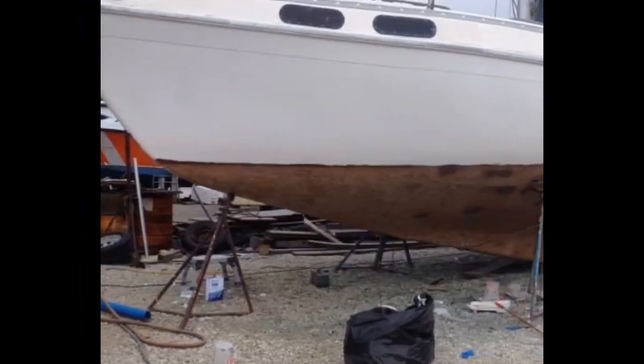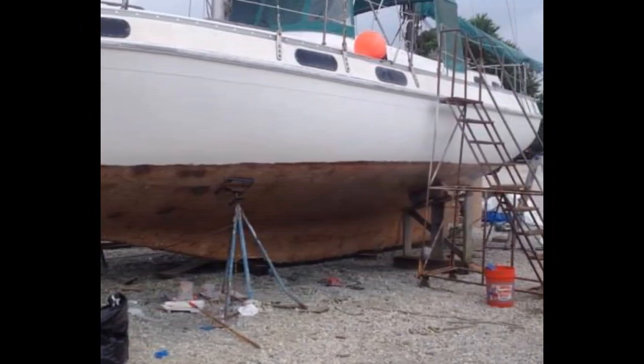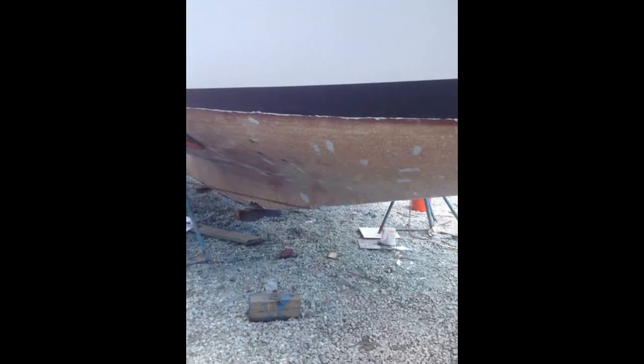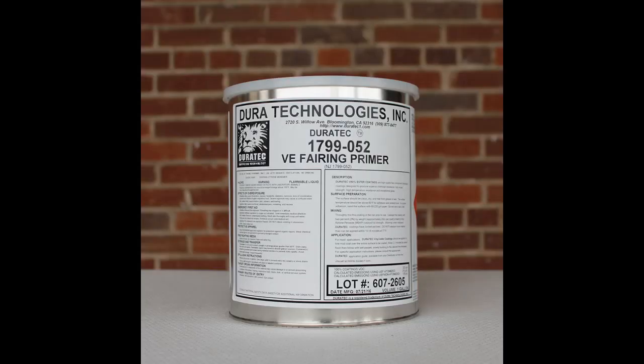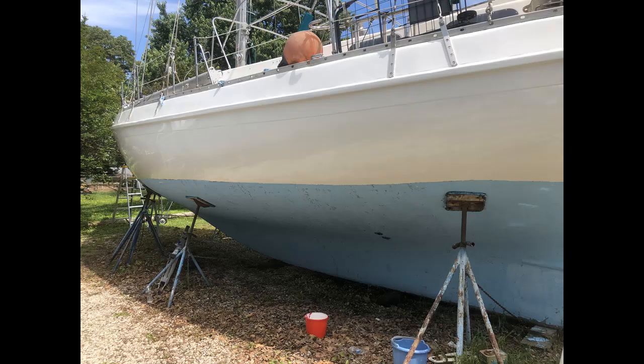After 3 months of letting the hull dry out, I applied 2 coats of vinyl ester to let it soak into the dry mat. Next, we applied additional fiberglass mat where needed, and then vinyl ester fairing compound to fill in the gouges. For this, we added 2 more coats of vinyl ester fairing primer and 1 coat of vinyl ester fairing compound mixed with filler to reduce sagging, and added micro balloons to make sanding easier. Our hull was ready to add new through hulls.